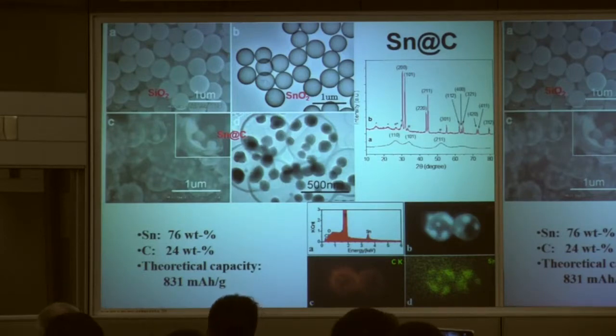Here you can see carbon microsphere covered with some tin nanoparticles. So in this case, the tin is 76 weight percentage, and the carbon is 24. And the theoretical capacity is higher than 800. You see, it's very high compared to the presently used electrode materials. Okay.